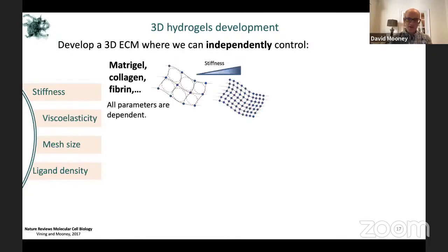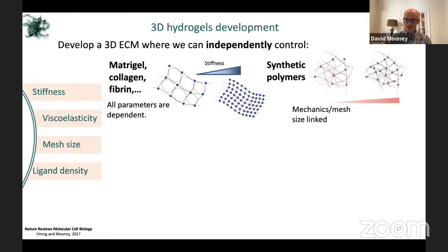Now, this will lead us to actually re-examine for a minute why we use these alginate gels. The reason we don't use materials like Matrigel or collagen or fibrin, as they are traditionally used in the biomaterials field, is that while one can readily make stiffer or less stiff gels out of these materials, this is typically done just by adding more and more material. And this makes the gels more stiff, but also increases the number of adhesion sites. It actually decreases the spacing between the gels, or the mesh size, which can lead to changes in diffusional transport of things like macromolecules. So all the variables end up getting basically dependent in this setting.